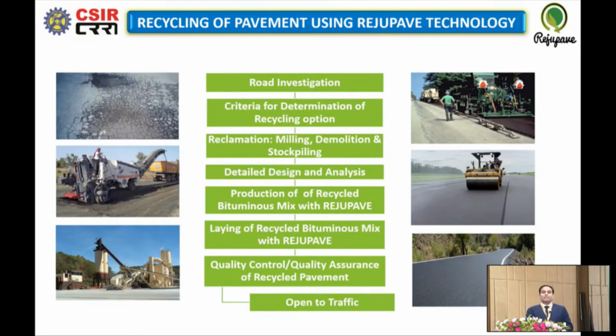This RejuPave rejuvenator retards the oxidation process of the bituminous mixes. So if you put this rejuvenator in the recycled mix, it will prolong the oxidation process. So whatever new surface you are laying, this surface is going to last at least 6 to 7 years. Oxidative hardening will be very slow in this type of surface.